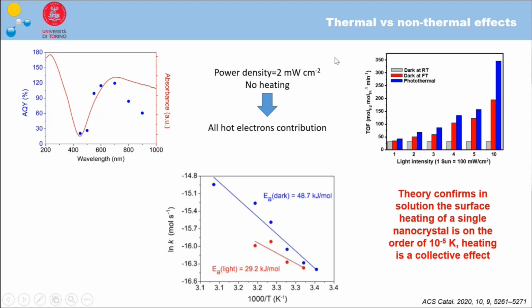And as you can see here from the plot on the right-hand side, if we use solar light with different intensity from 1 sun to 10 sun, we are able to increase by one order of magnitude the rate of hydrogen evolution, passing from the dark condition to 10 sun under photothermal condition. The red plots, as you can see here, are quite lower in intensity in comparison with the blue ones. Basically, the red plots represent the reaction rates measured in the dark at the final temperature generated under light excitation. So this gives a measure of how much the reaction under light is driven by temperature alone. So about half of the rate is given by the increase in temperature in the catalyst, and the other half is given by the production of non-thermal excited hot carriers within the materials.